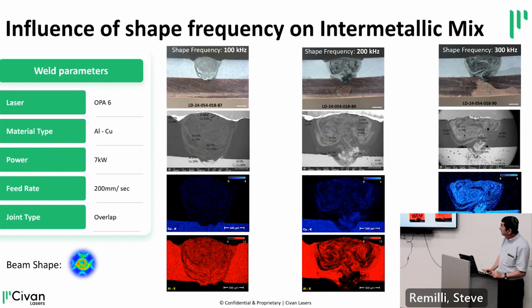And you can see that by changing the frequency, we are able to get here a perfect weld, okay, with hardly any intermetallic mixing. Whereas if you change some parameters, you get a lot of mixing. Okay, so again, the point is it's very difficult to do, but you have the tools to control it and really get a perfect weld.